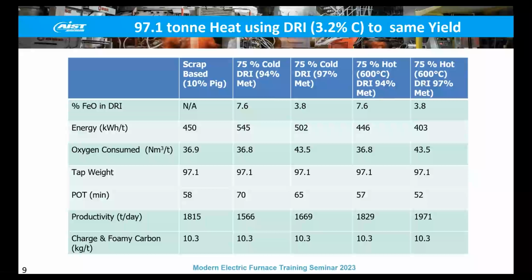Here's an example of hot charging. When you're hot charging, you get the benefits of all that extra thermal energy still present from producing or reducing the DRI and making pellets. So in this scenario, even hot charging with a high metallization, you're now outperforming the scrap-based system by this model, using less energy. Obviously, there was energy put into the system when making the DRI, which isn't being shown for the electric arc furnace side here. But your productivity is increasing, your electrical energy is decreasing, and your power-on time is decreasing.